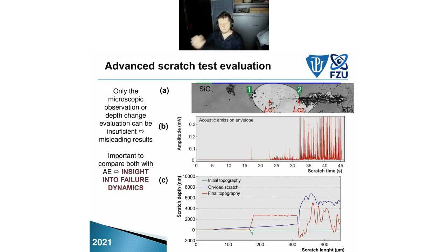Generally, we can check it during the depth change record. So we have 3 pass tests. First, topography, just checking the material, then the on-load scratch, and then final topography. In the initial topography, the green color, we can see the coating is okay, but there is some asperity going above the surface. The positive values are into the depth, the negative values are up from the sample. And during the onload, the blue phase, nothing is happening here.